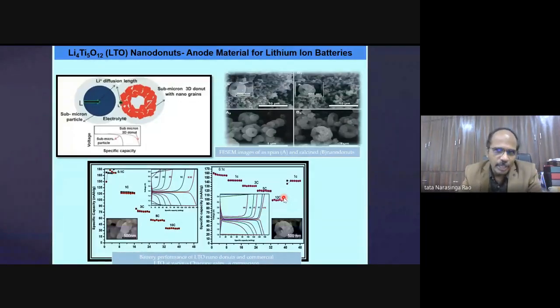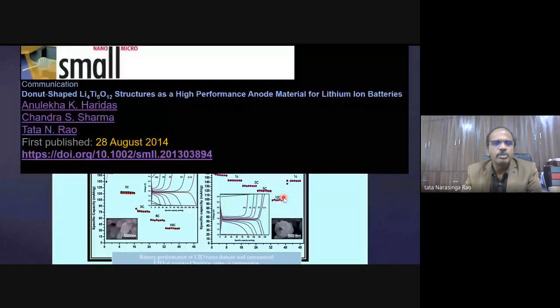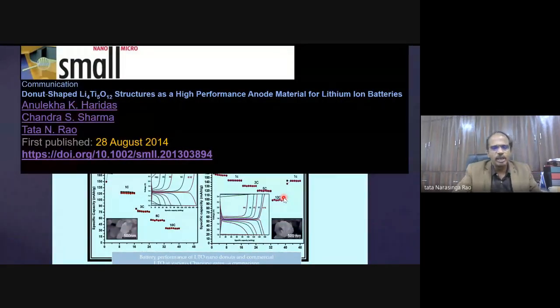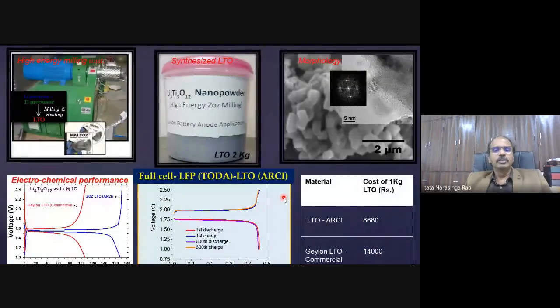And today it is not just our paper alone. We published in a good, high impact journal, Small, that time, in 2014 actually. And now we make this lithium titanate, if not donuts, in nanoparticles in kg level material, as you can see here. And you can see 600 cycles we do, and the charging and discharging remains same. And here we are comparing with one imported material, the red one, which has lower capacity than ours. We are performing much better.